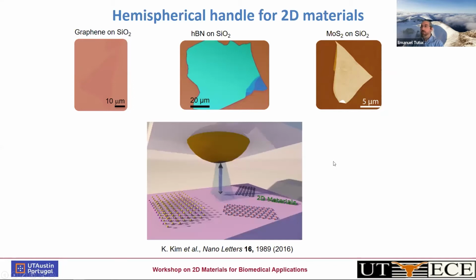In our lab, and I guess in a number of others, we would use a hemispherical handle that's shown here schematically that's coated with an adhesive polymer. And that allows us to pick up different nanomaterials and then also release them on desired targets. By the way, this type of technique could actually be adapted to other nanomaterials, not necessarily 2D materials, and that could perhaps have some practical applications for biomedicine.